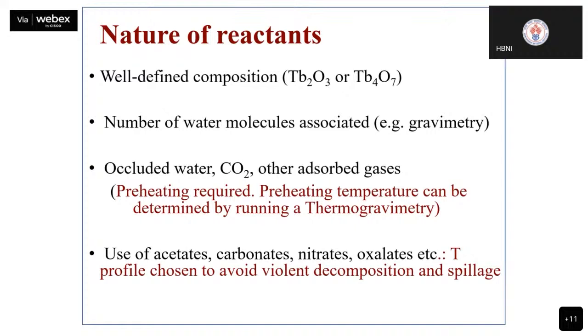One of the very first mistakes that I made when I was doing solid state synthesis in my initial two to three years was that I was preparing some compound with terbium. Terbium is a rare earth oxide, a lanthanide. Most of the rare earth oxides have the general formula M2O3: lanthanum oxide, Nd2O3, dysprosium oxide, gadolinium oxide. So I thought maybe terbium also has that particular composition. I did the calculation accordingly, but I didn't get the product.